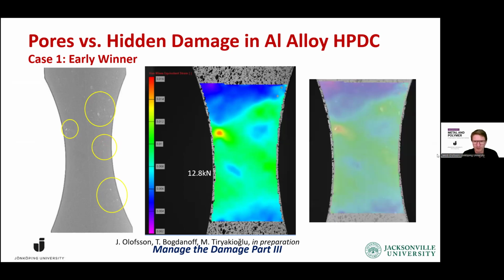And if we then combine these images and overlay the X-ray image on the strain field, we can see that there's something interesting going on here, because the porosity that we saw here is not connected to the surface, but we would expect the strain concentration to go towards the surface. But it's actually going to the right of the porosity. And we can see also in the central area to the right that there are porosities on the upper hand that are also matching with the strain increase that we see in the strain field. And also where they have the thinnest cross-section area, there are some small pores associated there.